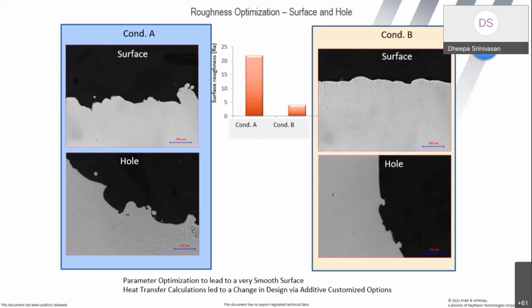So how we overcame it: we made a little bit of an intelligent overcoming of this challenge. We calculated how much pressure drop can occur for the compressor discharge air which goes through this hole. We took our CFD colleagues' help and they calculated the pressure drop. But as it turns out, we also found that the parameter optimization of the roughness did not give such a smooth and reliable roughness inside the cooling hole. So we took the pressure drop calculation by the CFD colleagues to our advantage.